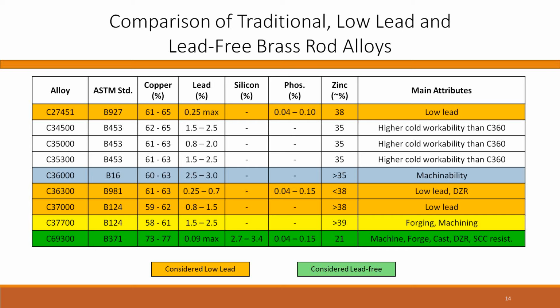The alloy that's in green is 693, and that's got a very high copper, low zinc content because that helps promote corrosion resistance. That has silicon in there that interacts with the copper and the zinc for machinability, and then that also has phosphorus in it for corrosion resistance, plus the zinc is in there for corrosion resistance too. And that alloy can be machined, cast or forged, and meets the requirements for corrosion resistance for PEX fittings, as does, to some degree, the 360 and the 27451, although those are kind of borderline.